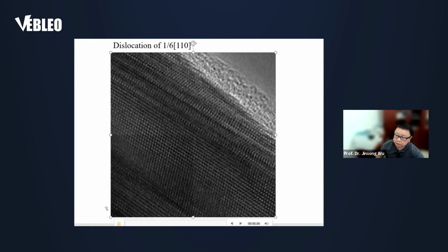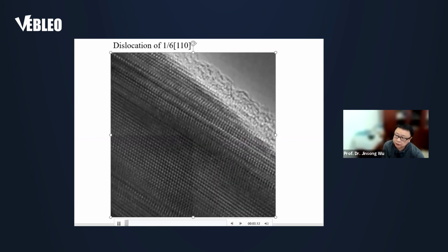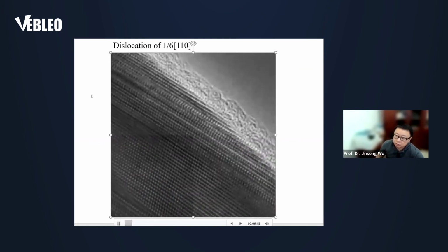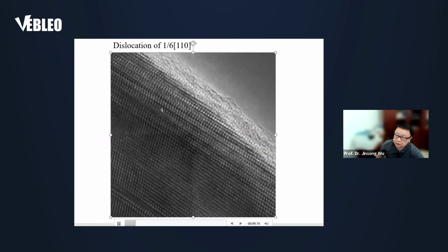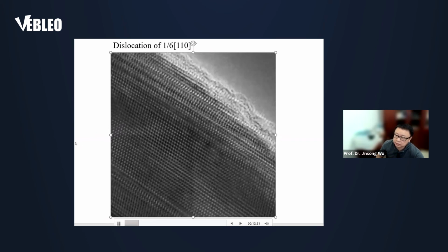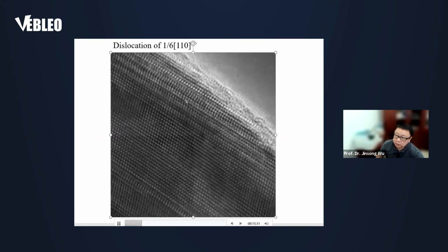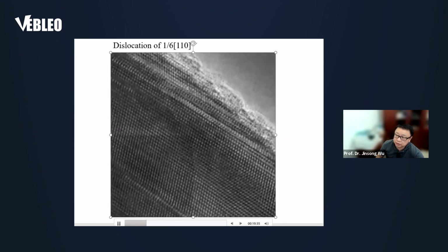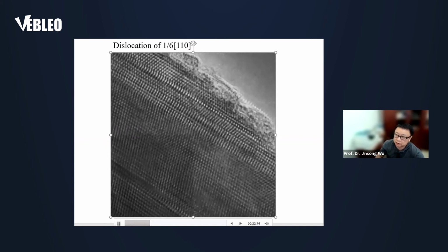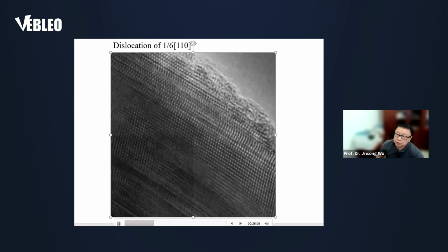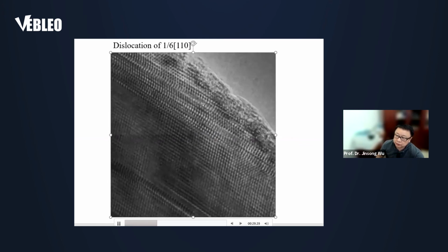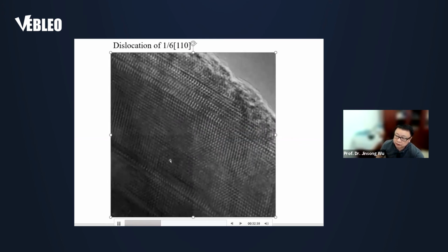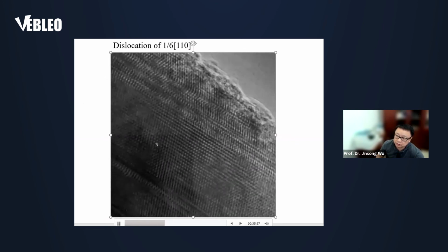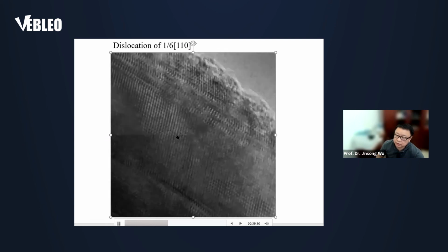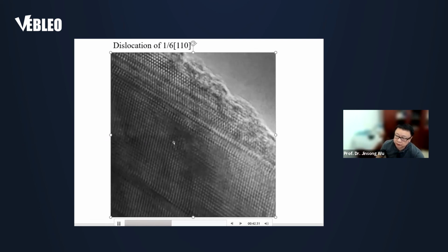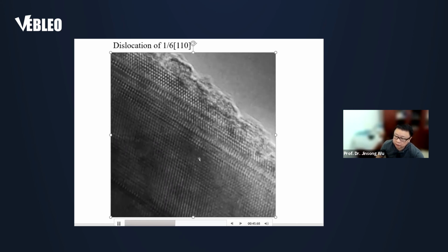And this video shows the structure changes during the delithiation. When we take the lithium out of the structure, the electron is also taken out from the other side. And now you can see there is change not only in the contents of these layers, but also the layers, which are pristine, are deformed greatly during the delithiation, especially in the faulted area. Here's a single crystal domain area. In this area, the structural evolution is not so big as in the faulted area.